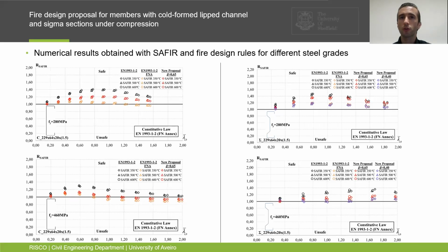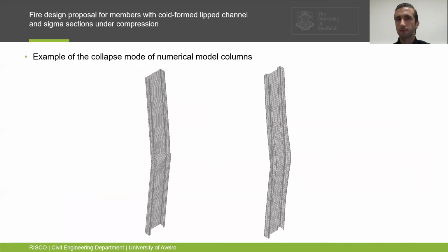The influence of the different steel grades is visible. Considering a low steel grade, the numerical results are far from the Eurocode 3 rules, the approximation improving when the steel grade increases. The current Eurocode 3 rules are still over-conservative, but the French National Annex tends to be increasingly unsafe for the results. The new proposal balances, once again, this difference, being often on the safe side, where the unsafe results only occur for the limit range of steel grade.